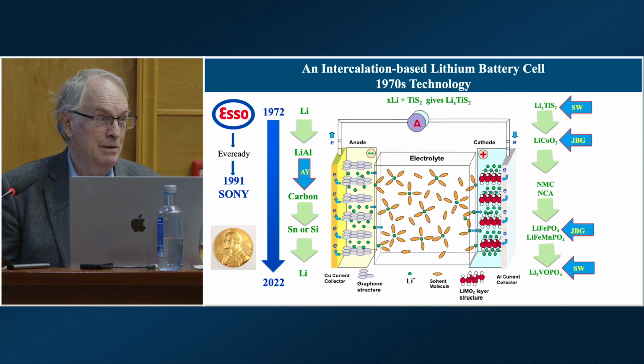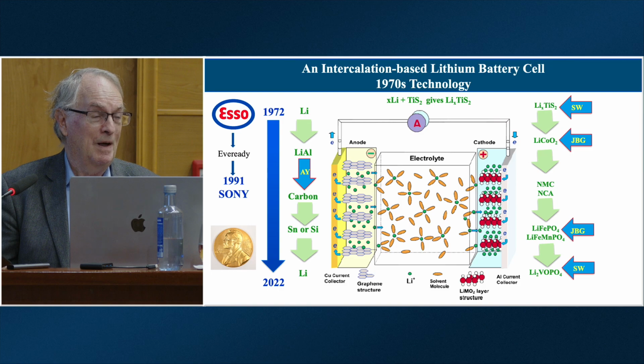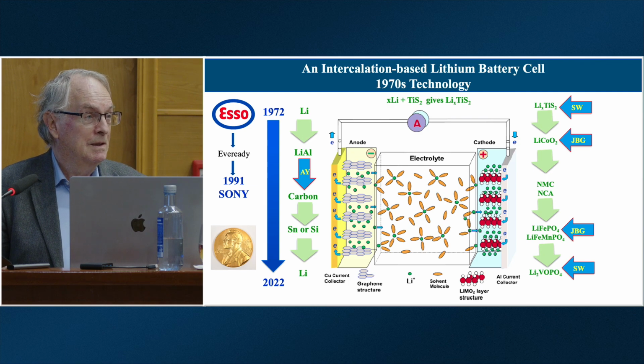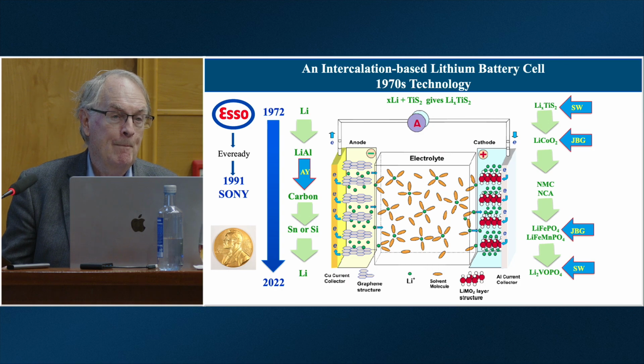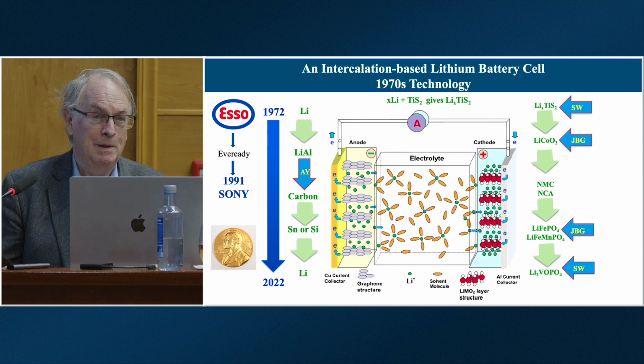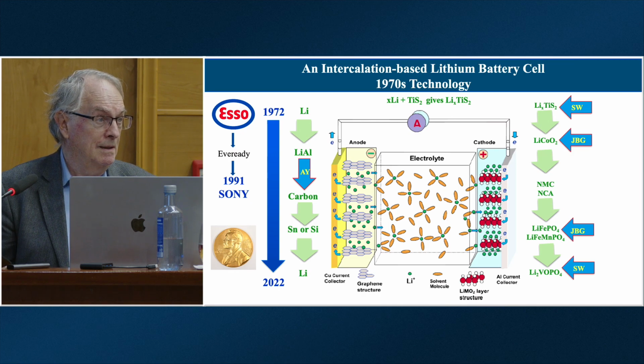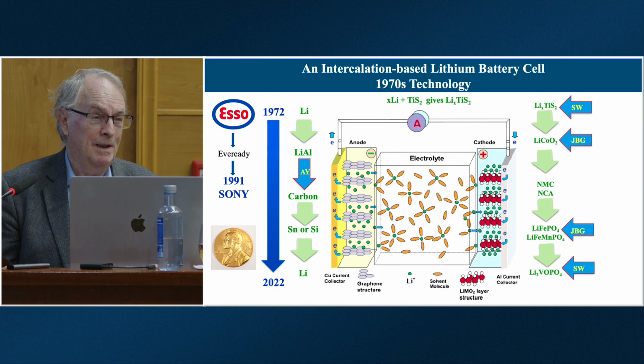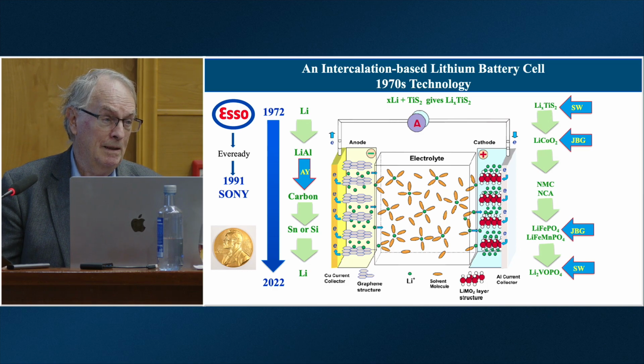The big issue is you need 72 grams of graphite to store 7 grams of lithium. And the graphite takes up half the volume of the cell. So if we want to increase the energy density, we've got to get rid of that graphite. So there's a lot of work now trying to go back to pure lithium, but as an intermediate, we and others are looking at tin and silicon. I know there's a number of folks in this region also looking at silicon as a potential anode.